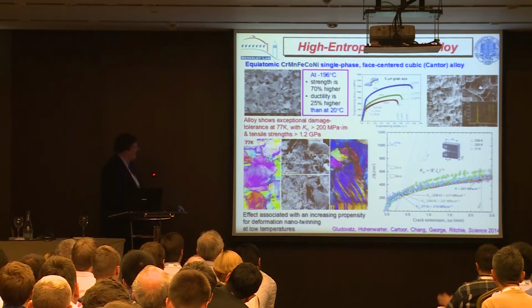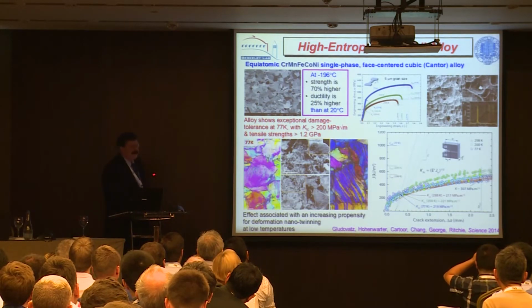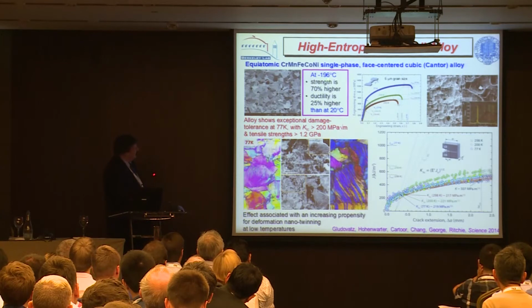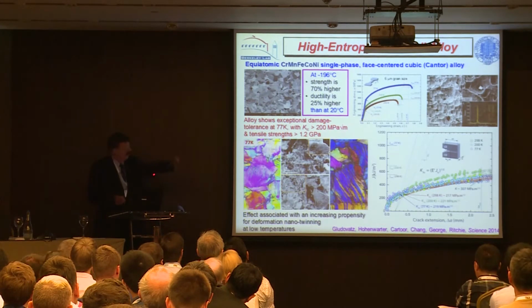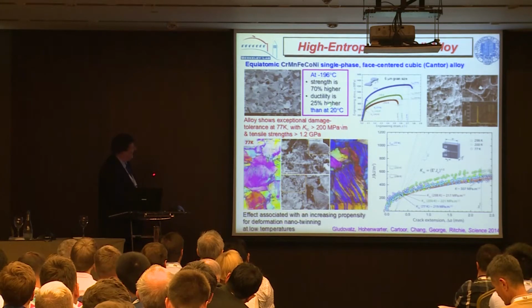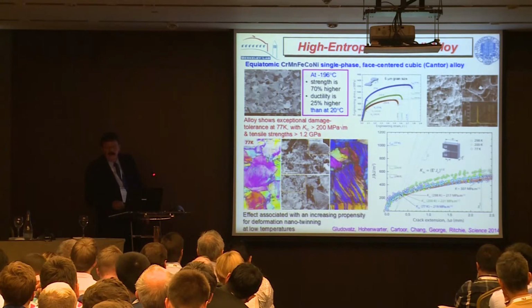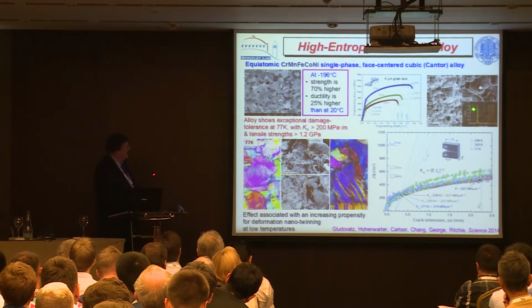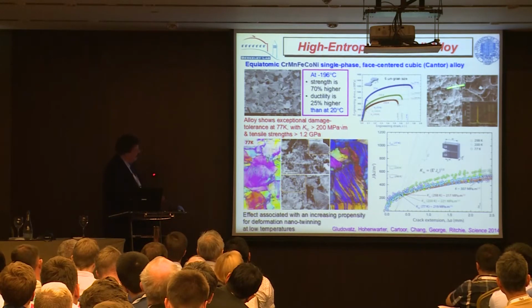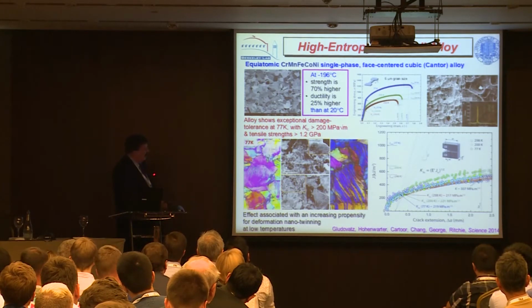But what's remarkable is that everybody knows now that when you go down in temperature, from room temperature to liquid nitrogen, it gets 70% stronger. Well, that's pretty obvious. But it also gets 25% more ductile. So we measured the toughness. Now we're in the intrinsic region now. This is all ductile fracture. We measured the toughness of this.